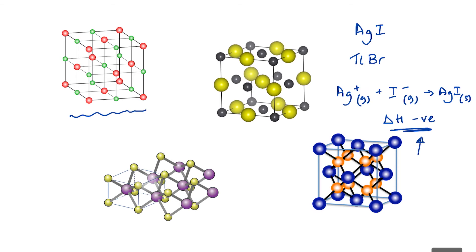So when we do the calculations we assume that we have got only electrostatic ionic interactions between our ions in the lattice. If experimentally our lattice is stronger than we would expect, then that's telling me that the attractions within the lattice are stronger and again this is more evidence that we've got significant covalent character in our silver iodide bond for example, more than would be expected given that it's an ionic compound.